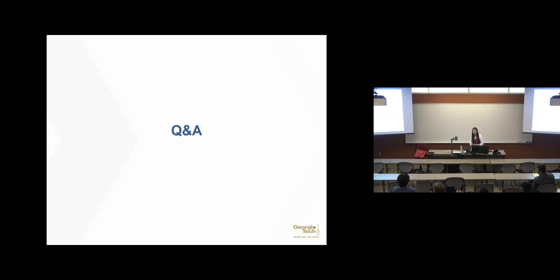So when you do the indentation, what kind of tip did you use? That's a very good question. Usually we use a spherical tip, because it doesn't generate a significant stress concentration, and a lot of these materials are like jello, so it's very easy to break. So we use a sphere, but we have a solution for different shapes of indenters. If you use a different shape of indenter to measure it, we can also extract the properties easily.